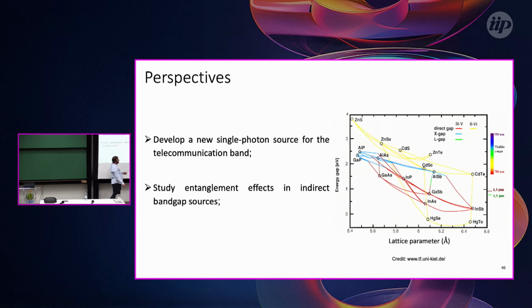If you change here the antimony concentration, you have a transition from a type 1 transition, direct band gap, to type 2 indirect band gap. But I cannot find anything about how this kind of transition, type 2, can influence the entangled properties of the quantum dots. This will give you better results or worse results. This is one of the things that I think there's plenty of basic physics that we can learn something.